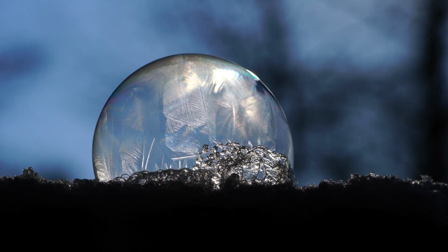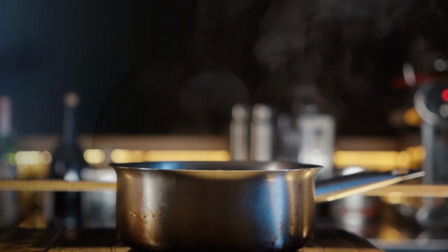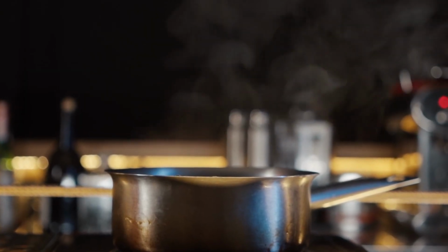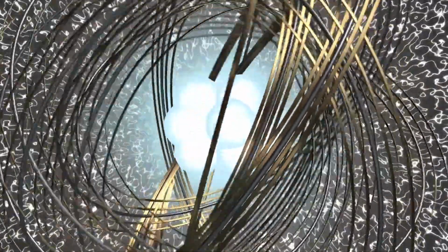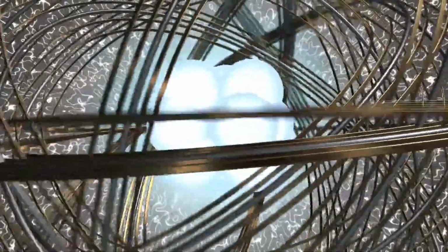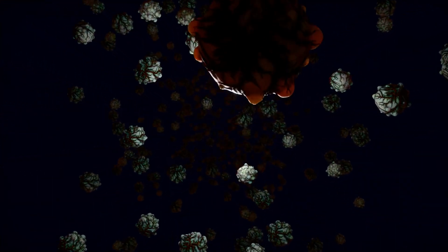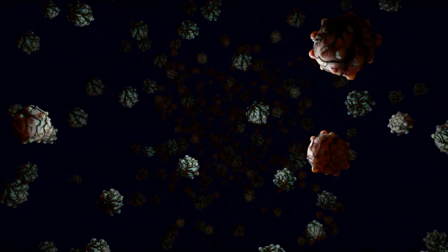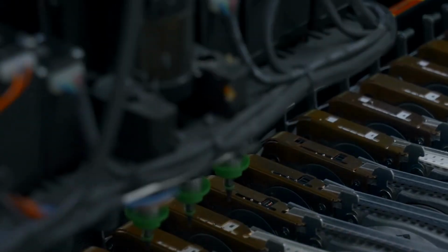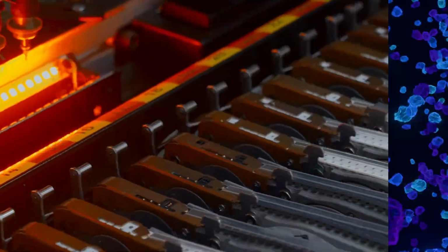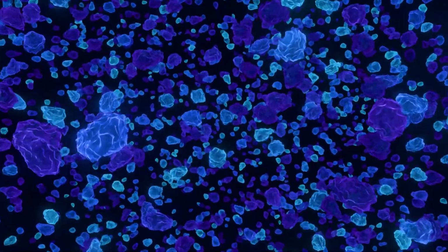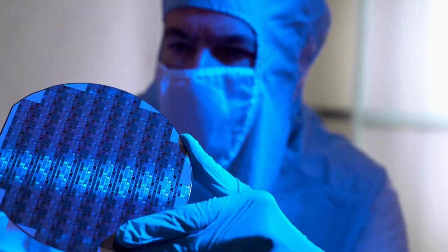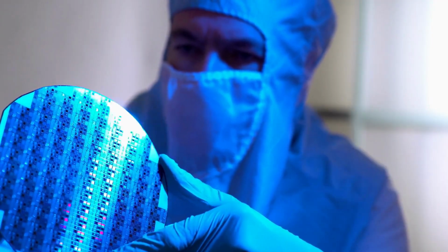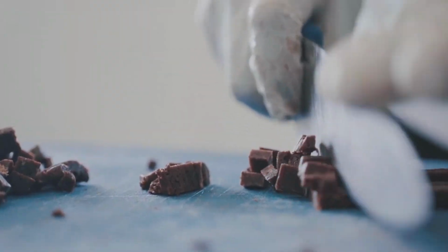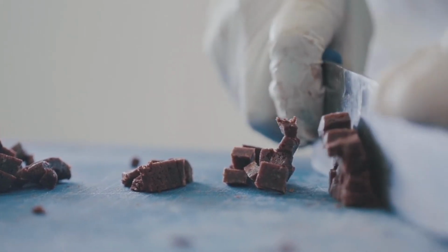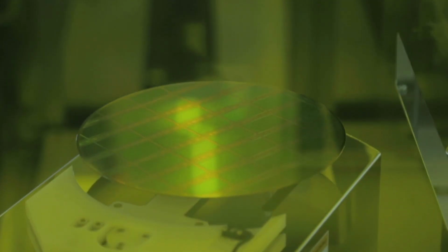Imagine trying to grow a perfectly ordered ice crystal, not by freezing water, but by condensing steam inside a furnace hotter than any flame, while keeping every molecule landing in exactly the right position. One stray contaminant, one pressure fluctuation, 1 degree of temperature variation in the wrong direction. Any of these can collapse the crystal's internal order into defects you cannot see with the naked eye. Defects that will only reveal themselves when you slice the boule, test the wafer, and find out what you lost.